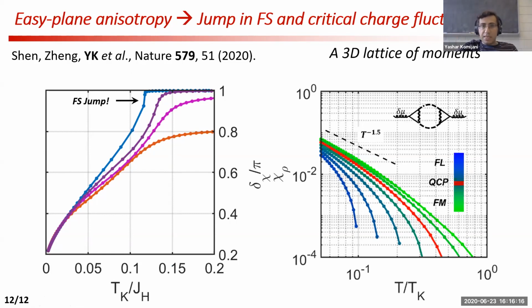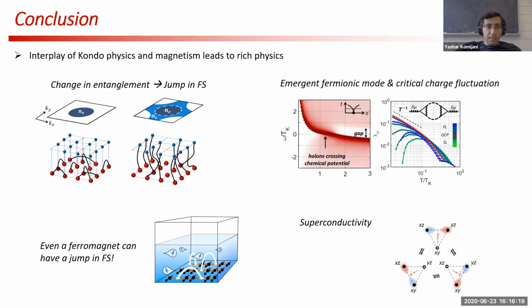So this brings me to my conclusion. I have a picture, but this picture is not completely backed by my calculation. So the picture is that on the small Fermi surface side, we have valence bonds or resonating valence bonds in the systems. And as these bonds snap to make singlets with the conduction electrons, we have a jump in the Fermi surface. So essentially, the jump in the entanglement, the patterns of entanglement, is associated with a jump in the Fermi surface. And this is accompanied by a fluctuation in the charge susceptibility, or a divergence of the charge susceptibility.